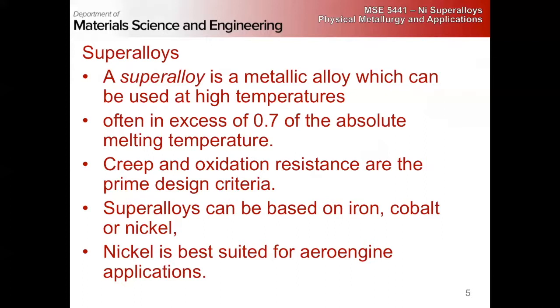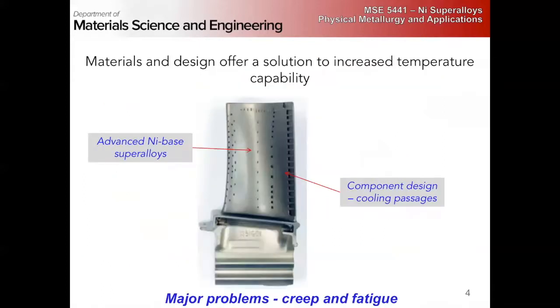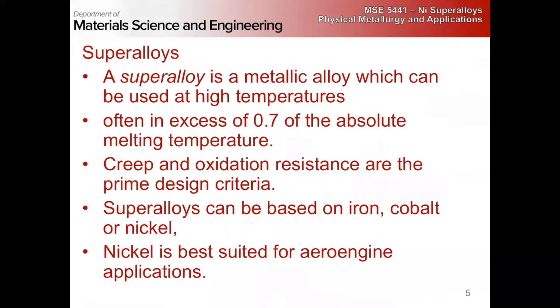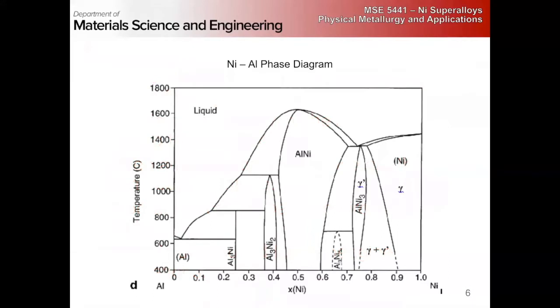to oxidize away. And there are superalloy compositions based on iron, cobalt, and nickel. We're going to focus just on nickel because that is by far the most commonly used for aero engines. Always for jet engines, you use a single crystal? Not everywhere we use single crystal. The blades are single crystal. The discs are polycrystal, because if you cast a disc out of a big single crystal, now you have anisotropy, right? The blades are single crystal for the most part.